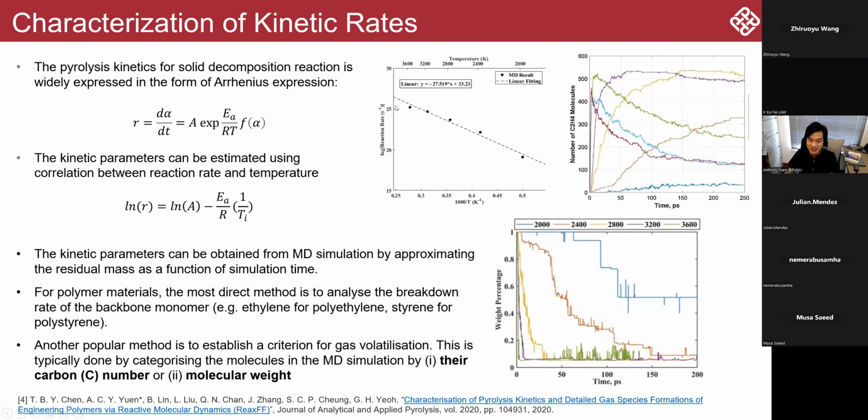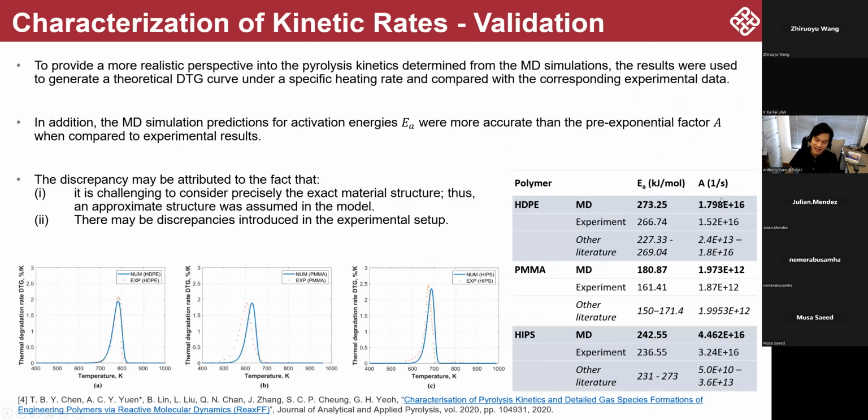So we did 5 different cases, and then we do a linear plot to get the slope so that we can identify the reaction rates. Basically, we find that for a simpler molecular composition like polyethylene, which is essentially a polymer chain of C2H4, we can get it very precisely because the reaction force field for C and H are pretty good in MD.